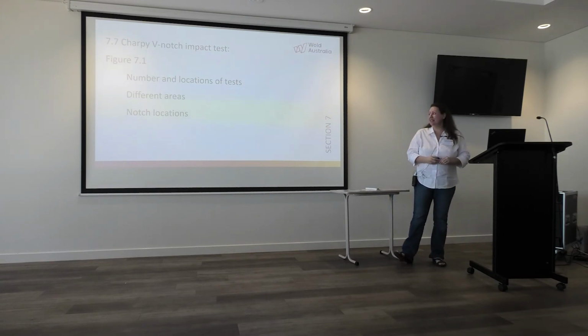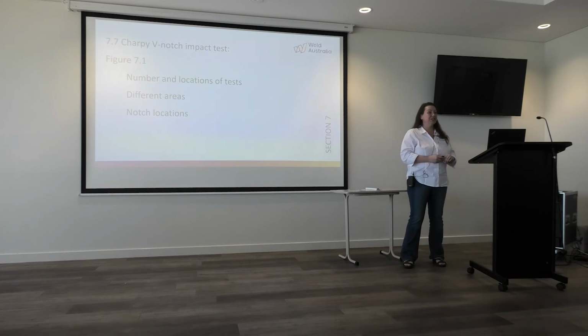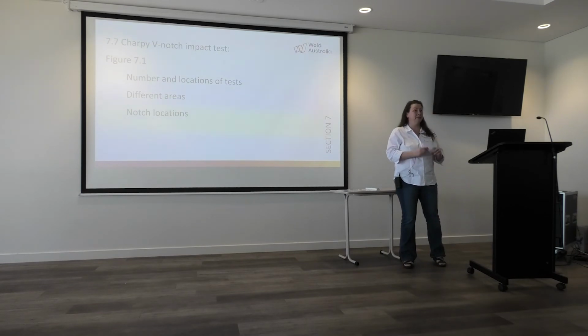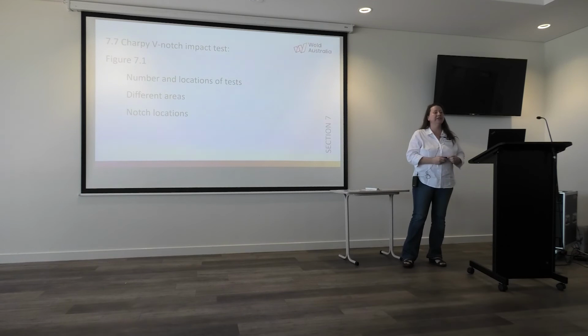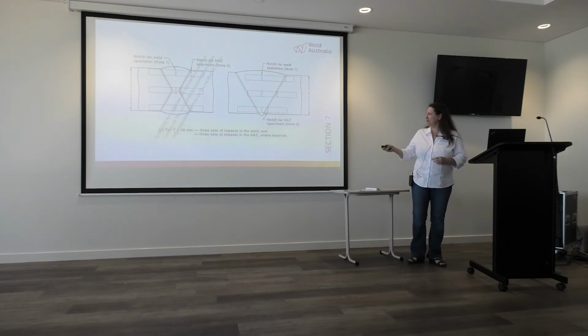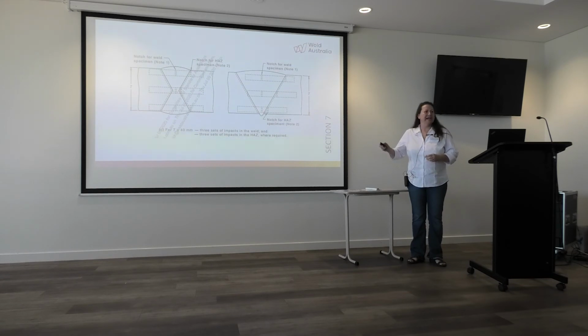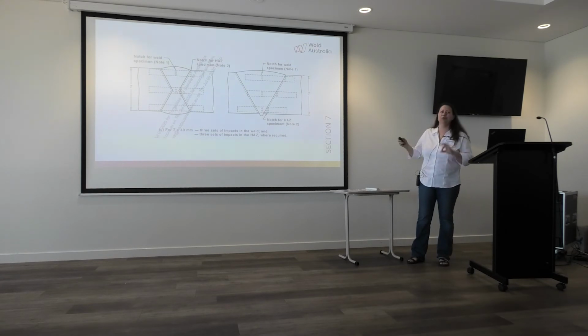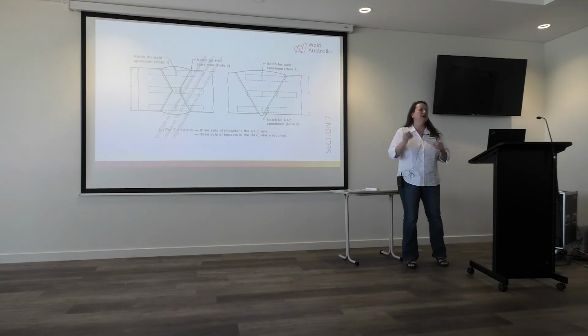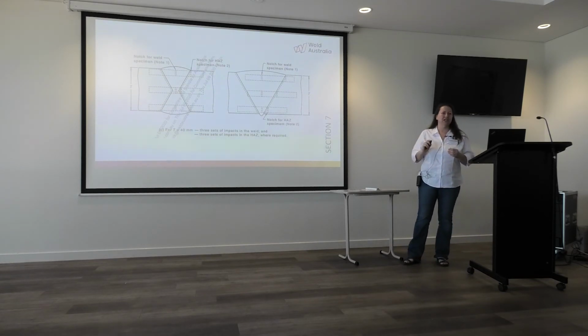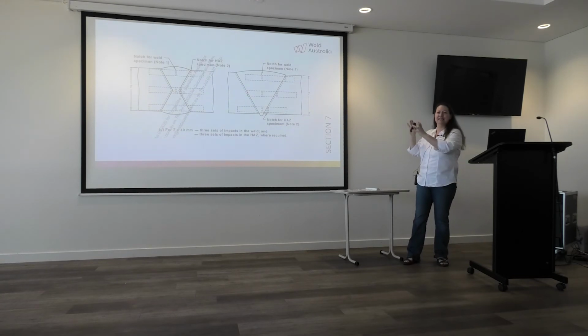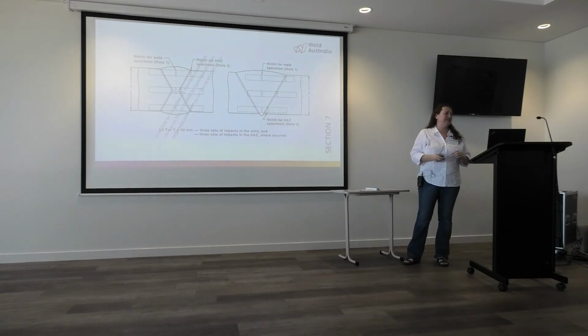Charpy V-notch testing changed a lot as well. The number and the location of tests would change, especially with the thick components. We'll get to that in a moment. So for different areas, with the notch location specifically recorded. Previously, you did one test here on the bottom and 2 on top. And now to test a location, you do 3 sets per location. So at the weld root and in the HAZ, center of the weld and the HAZ, center of the weld and the HAZ. And if you've got dissimilar metal welds, you test both heat affected zones. So this just clarified it and brought a bit of sanity to toughness testing.